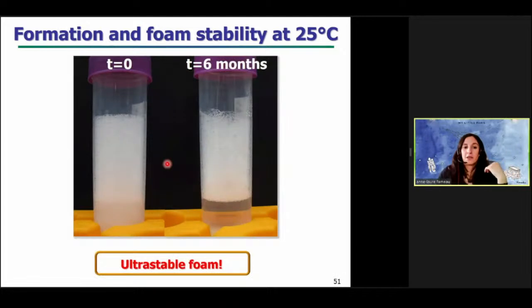Then we compare a picture of foam taken just after foam formation and after 6 months of conservation of the same foam at room temperature. We can see that the foam volume didn't change and the bubble size almost didn't change. So with this simple fatty acid system, we obtain ultra-stable foams.